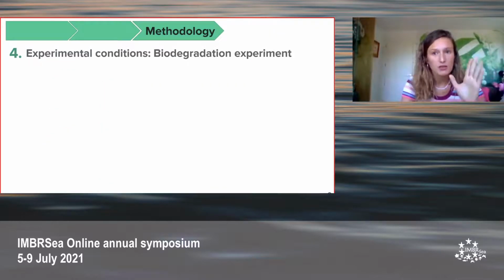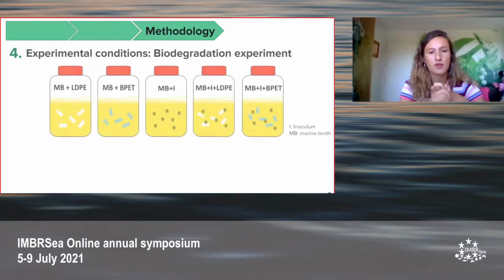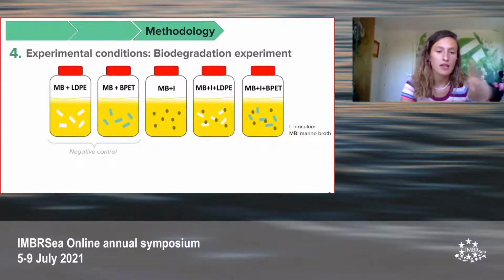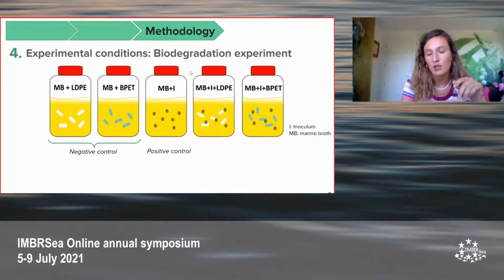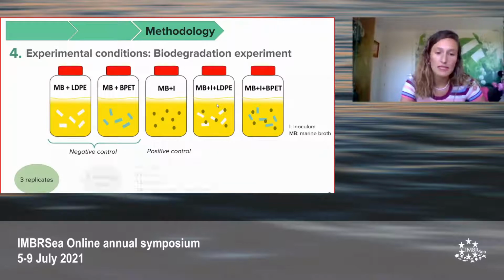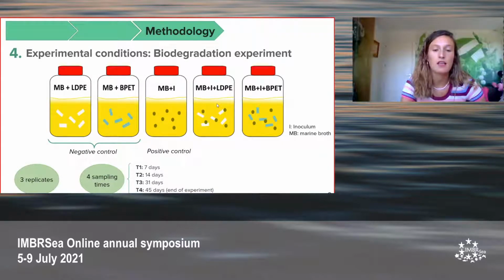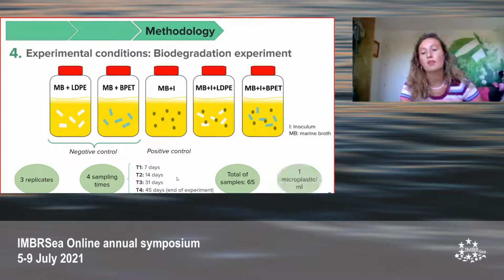Okay, moving into the biodegradation experiment, it consisted of 5 treatments with 2 controls. The negative control with the microplastic particles and without the inoculum, and the positive control with the inoculum but without the plastic particles. And the other 2 treatments with both the polymer and the inoculum. We used 3 replicates, 4 sampling times after a week, after 2 weeks, after a month, and after 45 days, with a total of 65 samples and with a concentration of 1 microplastic per milliliter.